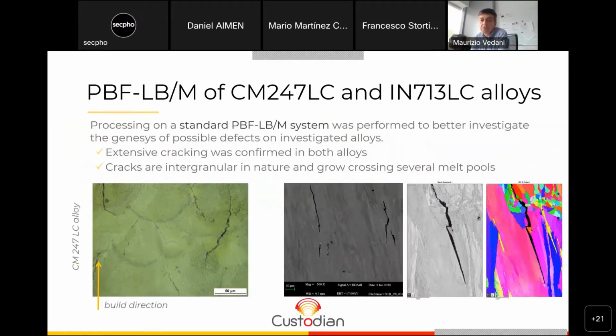Here, as I mentioned before, we made some tests according to a standard powder bed fusion by laser beam process to investigate the genesis of the possible defects and what kind of defects we had to face with our 2 reference alloys. And actually, it was readily confirmed that after solidification, a lot of cracks could be formed in the material by a standard process. I want to be clear, by a standard PBF process.